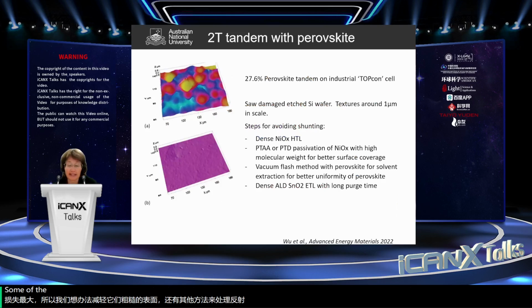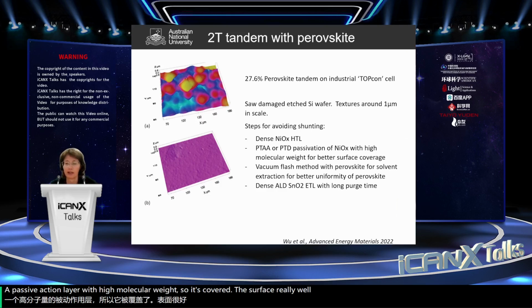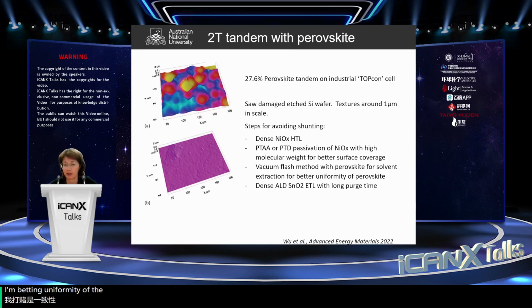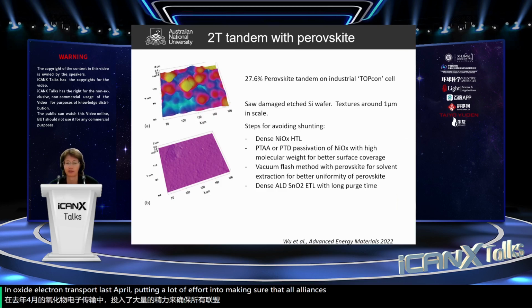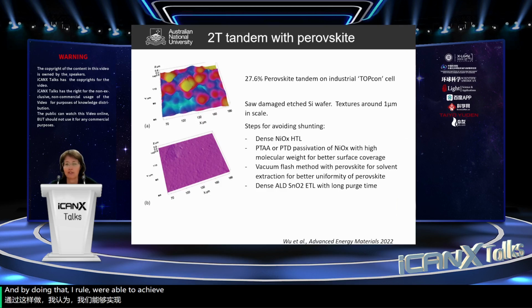Some of the key things that we found were necessary to avoid the shunting were a dense nickel oxide hole transport layer, a passivation layer with high molecular weight, so it covers the surface really well, better uniformity of the perovskite using the vacuum flash method, and a dense tin oxide electron transport layer. So overall, putting a lot of effort into making sure that all our layers were dense and highly uniform. And by doing that, overall, we were able to achieve a 27.6% efficiency perovskite tandem on an industrial compatible TOPCon cell.